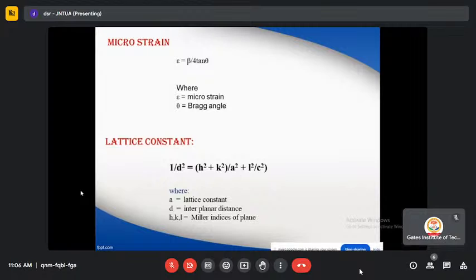So from the outcome we can say that a, b, c values are found to be reducing consistently from 0.57 to 0.49 and 0.67 to 0.54 by varying the cobalt concentration from 0.2 to 0.6. It may be achieved due to the substitution of lead cations of high ionic radius by the cobalt cations of small ionic radius. Also, for this 0.8 concentration, which is in the rhombohedral phase,